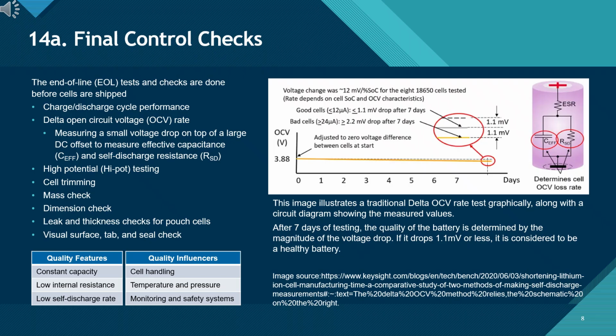Step 14A for final control checks. EOL testing. In the final control stage, each cell undergoes a comprehensive set of end-of-line tests to verify compliance with performance and safety requirements before shipment. We begin by confirming charge and discharge behavior, verifying that the cell delivers the expected capacity without abnormal resistance growth.